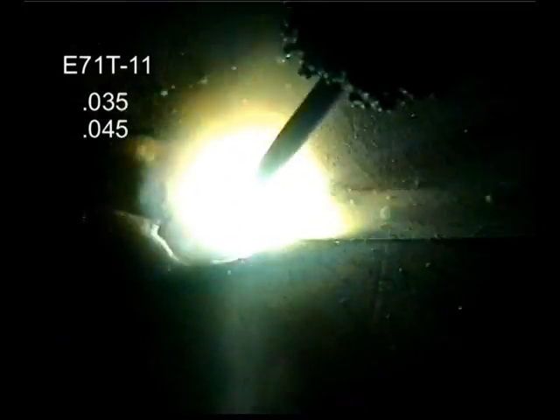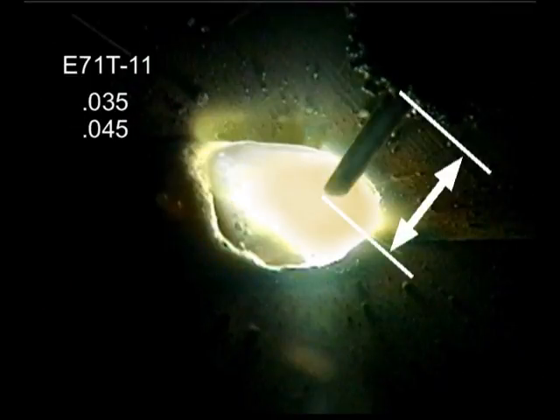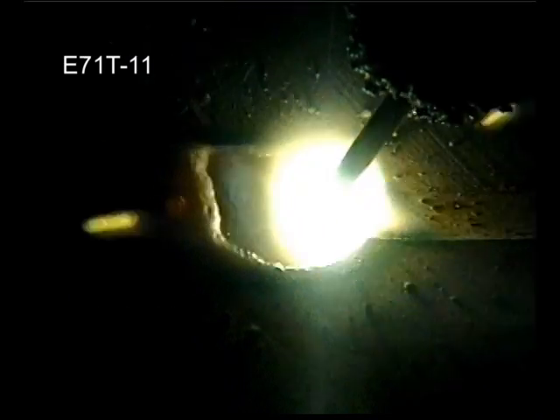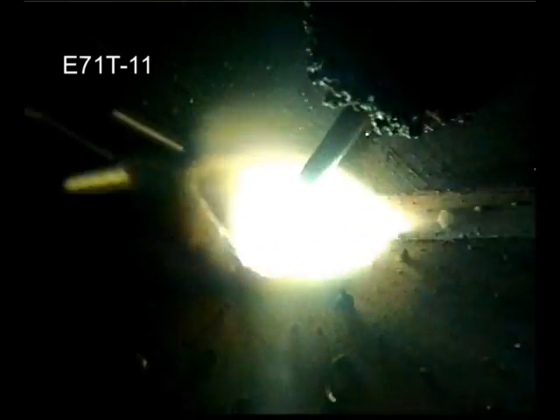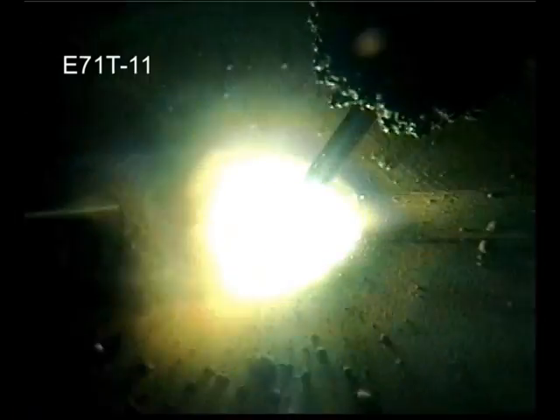Depending on the specific wire and wire diameter, the recommended electrode extension can range from 1/2 inch to 2.5 inches. For the smaller E71T11 self-shielded wire we're using, the wire stick out from the contact tip to the metal should be around 1/2 to 1 inch. For a smooth weld bead, you want to maintain a consistent wire stick out.